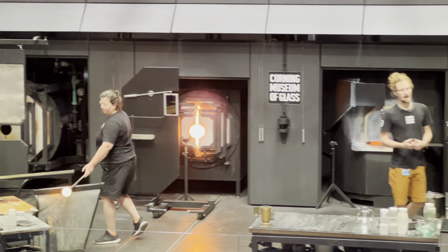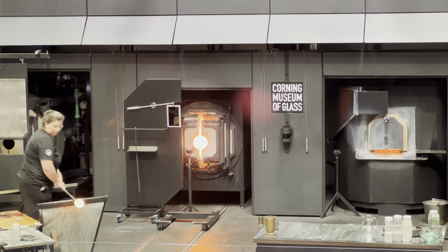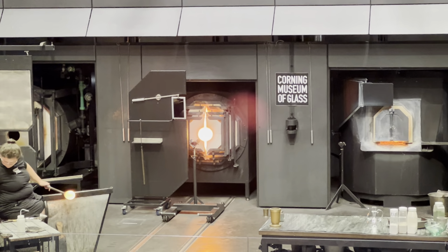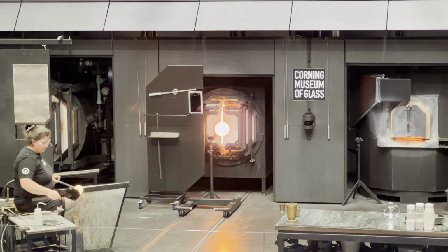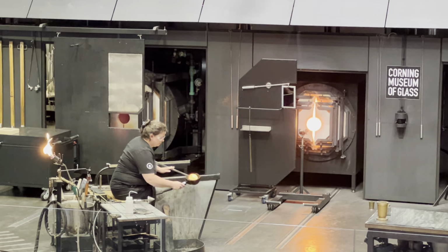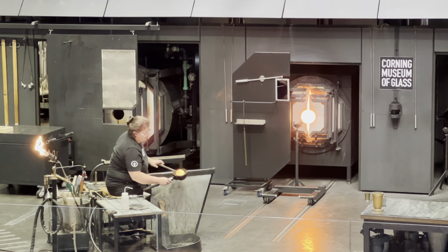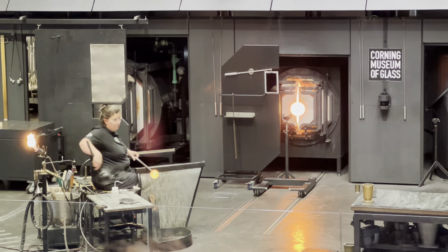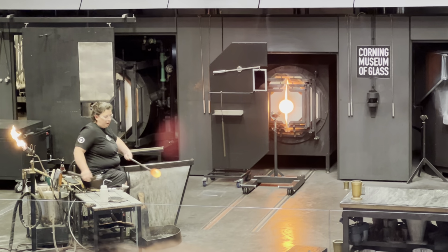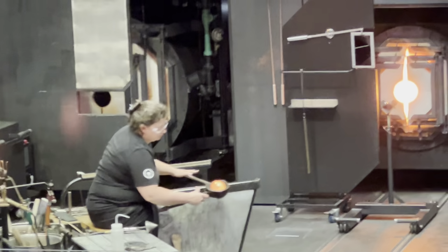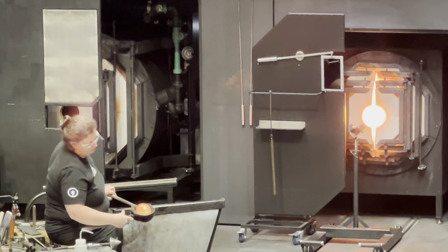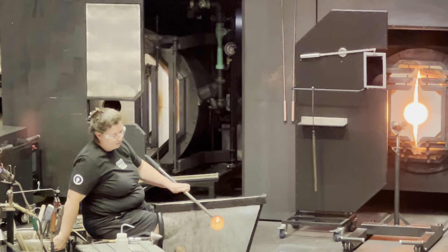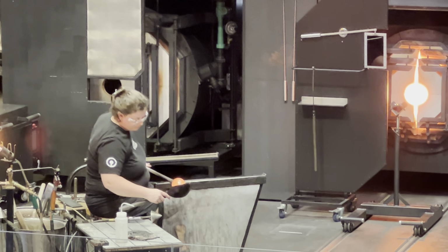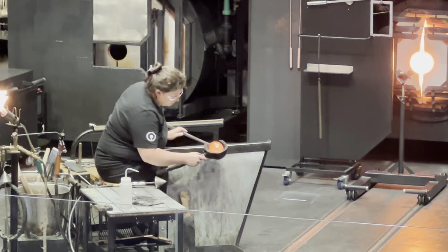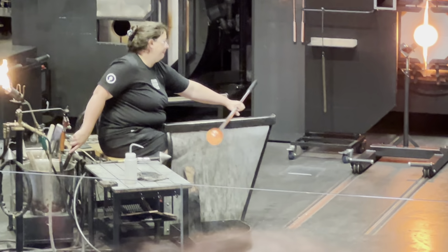Now, with every subsequent gather, we do get more and more material. If we try to get this much glass that first time, all of it would just run off the end of the pipe. It would drip all over the floor because that glass is too runny to support its own weight. So a larger wooden scoop shapes, centers, and cools that fresh glass around that first bubble. These wood tools, soaked in water, last a couple of years before we have to replace them. The water turns to steam and then the glass glides on the layer of steam within that tool. So while we cool off that fresh layer of glass, that internal bubble, it's warming back up, it's softening so that we can continue shaping and inflating.